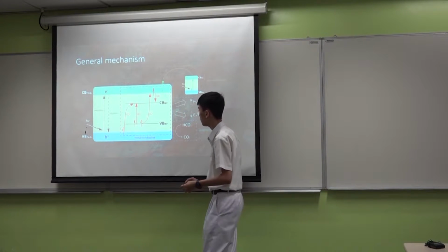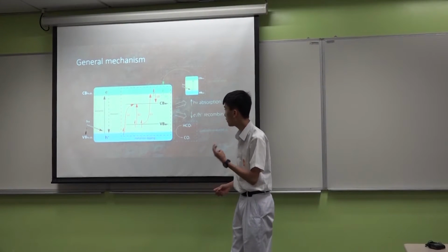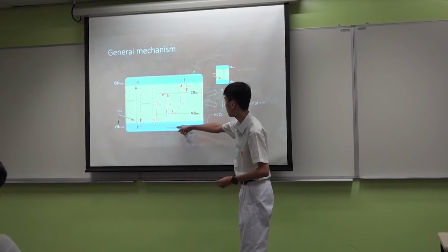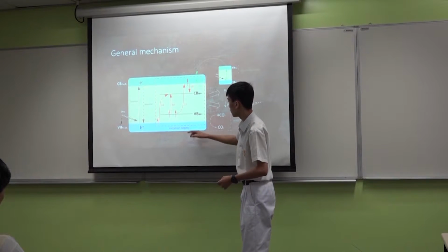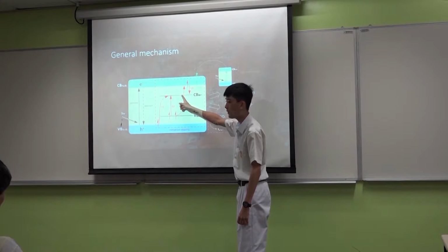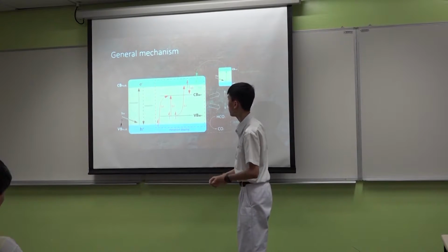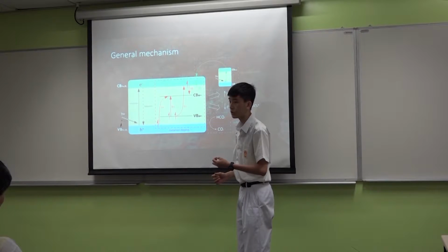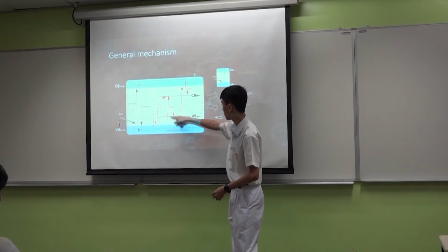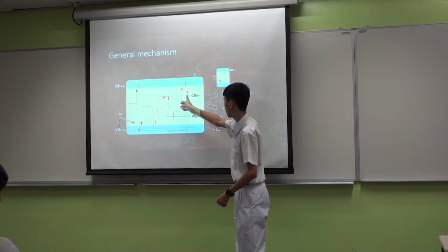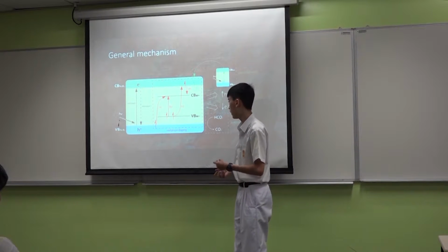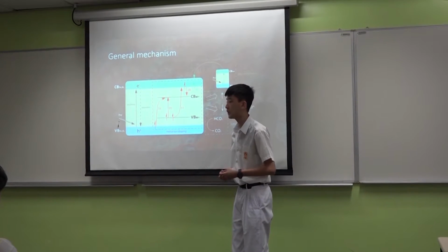Metal ion doping provides three extra ways for electron promotion. The first one is from the valence band of iron(III) oxide to the conduction band of the metal ions, and it can also promote from the valence band of the metal ions to its conduction band or to the conduction band of iron(III) oxide directly. Besides, we can reduce the recombination rate of iron(III) oxide through electron trapping. After photoexcitation, the electron may fall back to the conduction band of metal ions instead of falling back to the valence band again, so the hole will not be filled up and the recombination rate can be reduced.